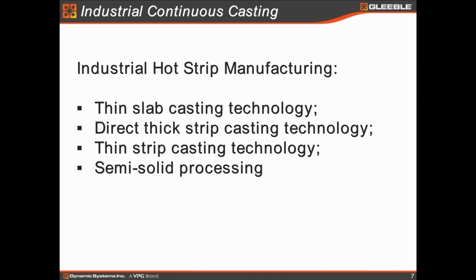And again, as I said, casting is just part of the steel processing. So you have to combine it with the industrial hot rolling as well. But before that, we have strip manufacturing or casting technologies developed from thin slab to direct thick strip casting to thin strip casting. But in all these, in order to make the subsequent rolling even more efficient, people are using semi-solid processing as well. In other words, you are deforming the steel billet, no matter how thick it is, while the core is still in a liquid zone. So we call it semi-solid processing.